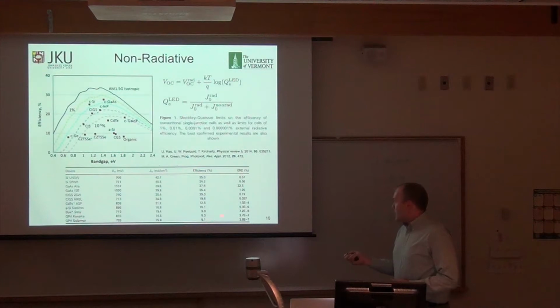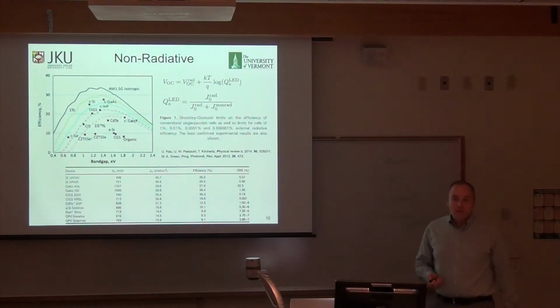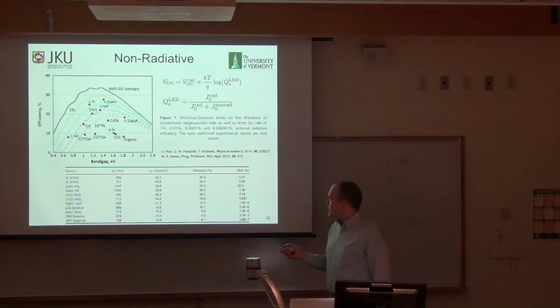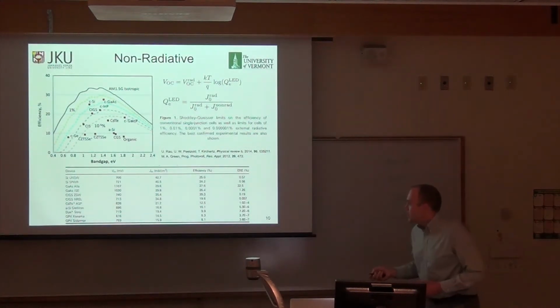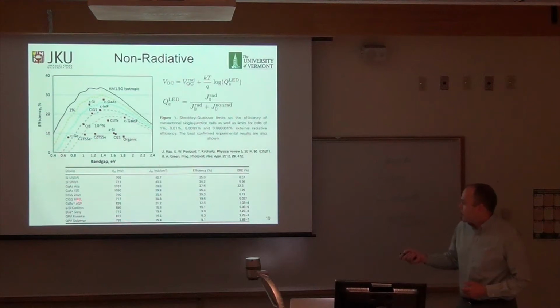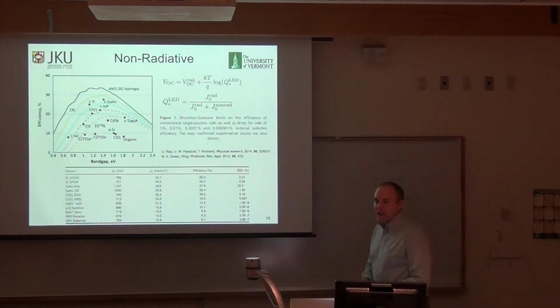And these are, coincidentally, the lower efficiency solar cells. So we're looking for materials that have high radiative recombination efficiency and therefore very small loss in VOC. Coincidentally, all of these materials down here—amorphous silicon, dye-sensitized solar cells, organic photovoltaics—are new technologies that people have been very excited about looking into for the past 10, 20 years.